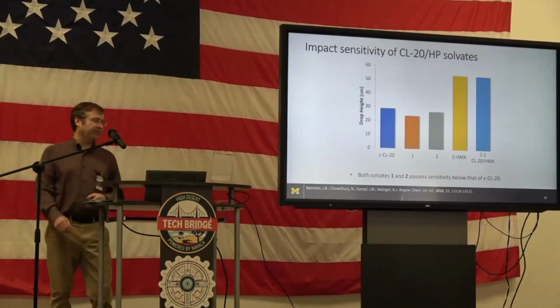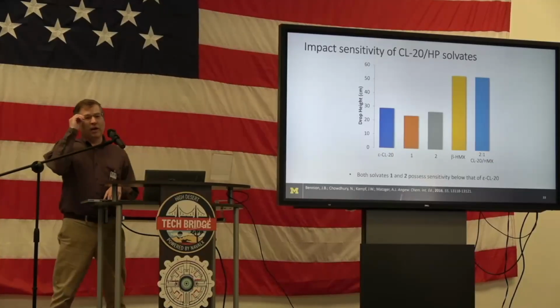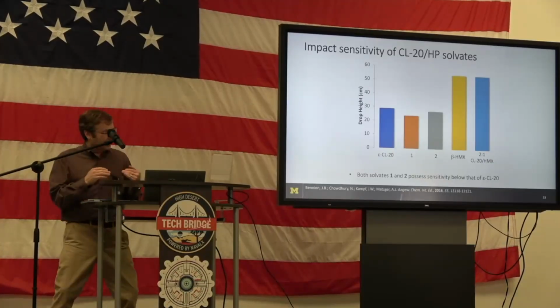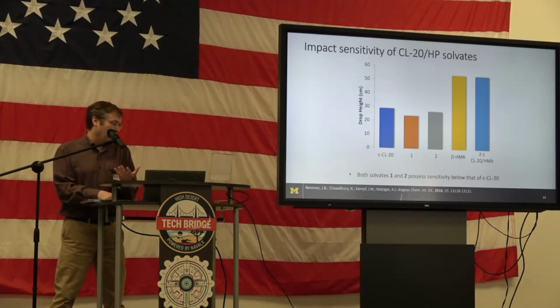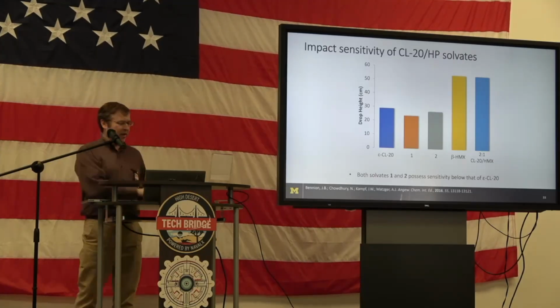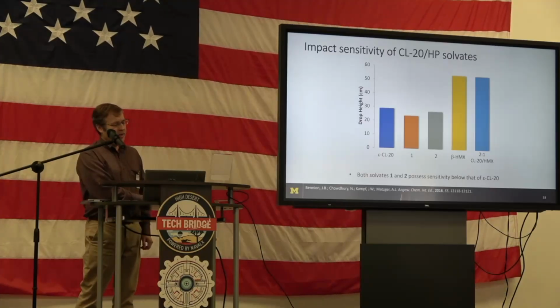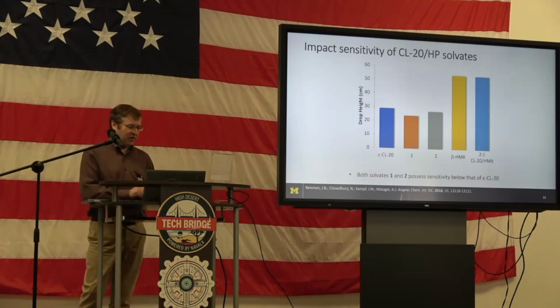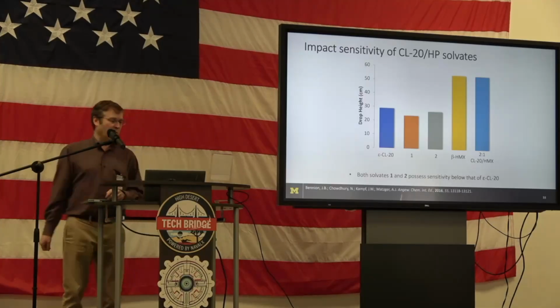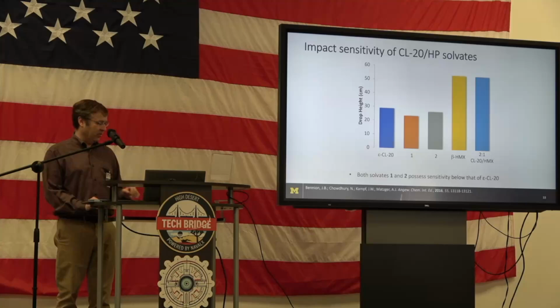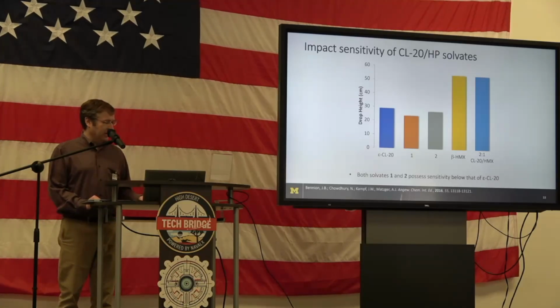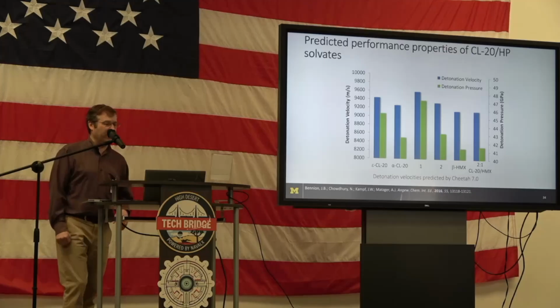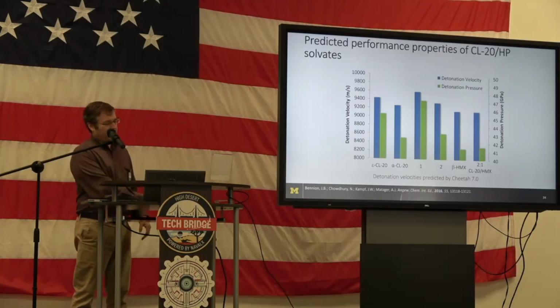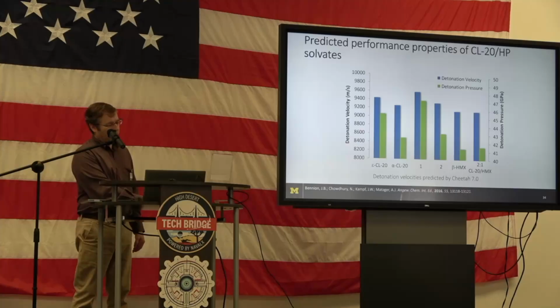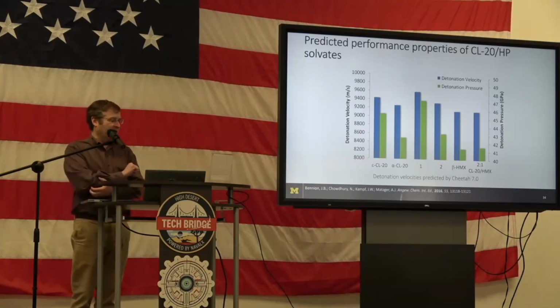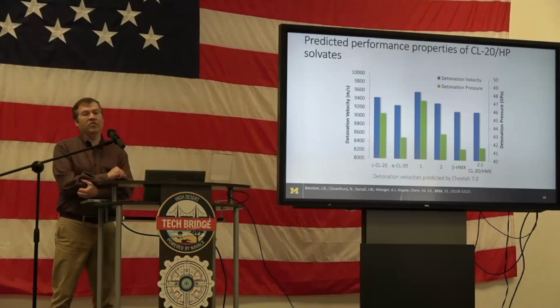Okay, so what does it do to our impact sensitivity? That's our first question. Well, the impact sensitivity does get a little bit more sensitive. We have hydrogen peroxide in there, and indeed, relative to epsilon CL-20, it's now a little bit more sensitive, much more sensitive than the 2-to-1 CL-20 HMX crystal I was telling you about. But then we can look at our performance projections with Cheetah, and we can see that for the more dense form, we are predicting substantial increases in detonation velocity and detonation pressure.